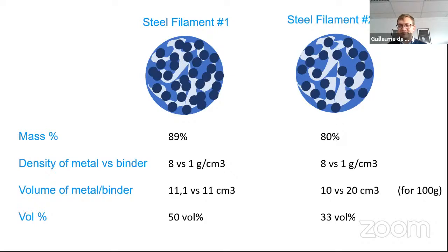In one case, you have a target, which is 50 volume%, and in the other case, you have only 33%, which might look great, but will not be enough to get a dense metal part at the end. This is also true for ceramics, by the way. This is one of the most important aspects